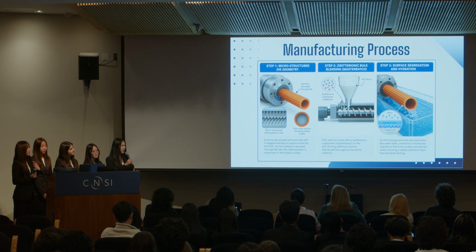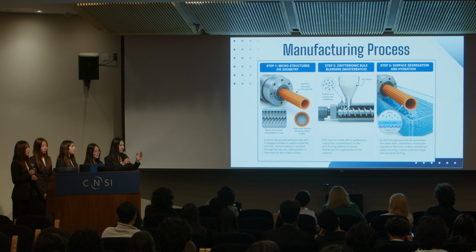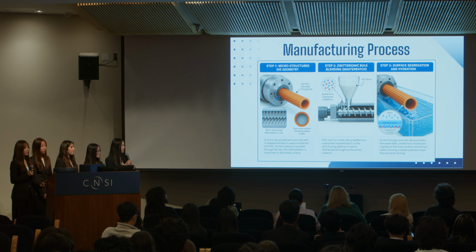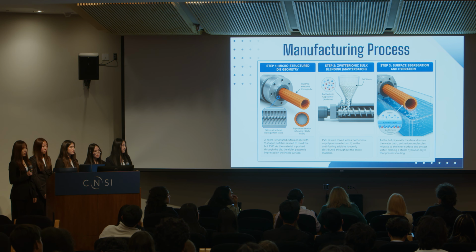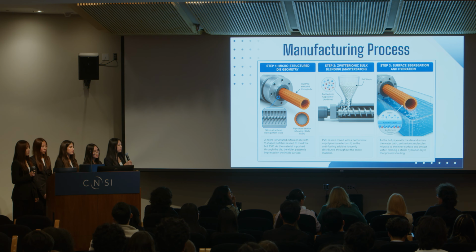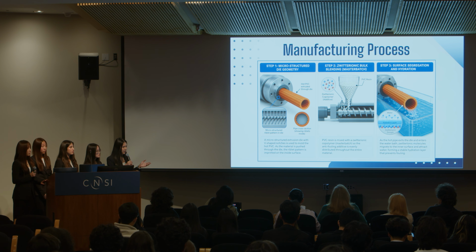Essentially, we're running water through the pipe, and these Zwitterions are polar, and water is also polar. So these amphiphilic molecules will migrate towards the inner surface of the pipe, allowing the Zwitterions to be more effective. Is there going to be Zwitterions throughout the thickness of the pipe, not just on the surface? It's primarily, so we do that water step to bring these Zwitterions towards the innermost part of the surface, so that when water is going through it, it'll create that hydration barrier.